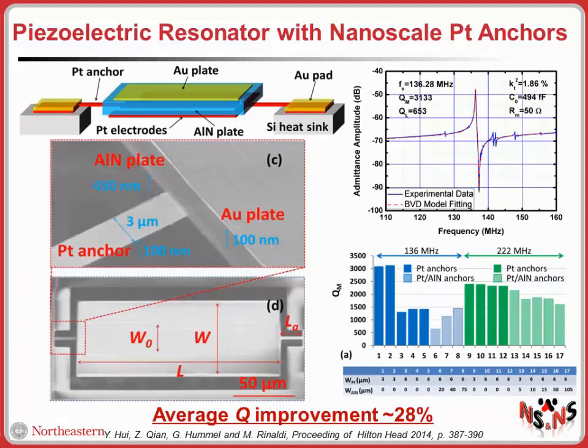And here you see one of the prototypes that we demonstrated. So these are 500 nanometer thick aluminum nitride plates, which are anchored to the substrate using these very tiny metal anchors. You see the anchor is only 100 nanometer platinum thick, and the width is about 3 microns. So what is very interesting, first of all, is the electromechanical performance of these devices.